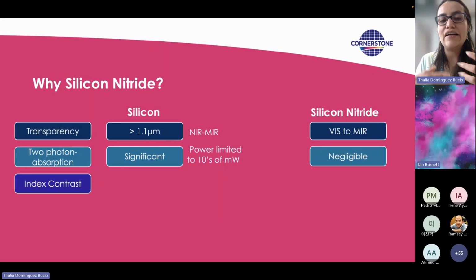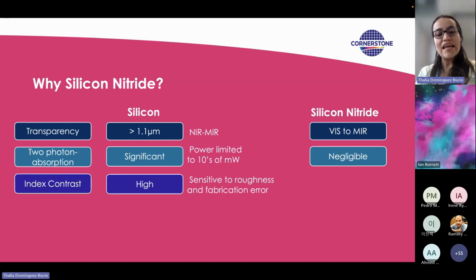Then, if we look at the index contrast, as I mentioned before, one of the advantages of silicon is that it has a higher refractive index contrast, which means that we can fabricate very small devices. Now, the problem with that is because it's a very high index contrast, the devices that we fabricate are going to be very sensitive to roughness. So every time we etch our waveguide, we will have some roughness in the sidewalls, and that will increase the losses of our waveguides. And on top of that, because the devices are so small and the refractive index is so high, if we have some fabrication error, then the response of our device can vary dramatically with respect to the target response.